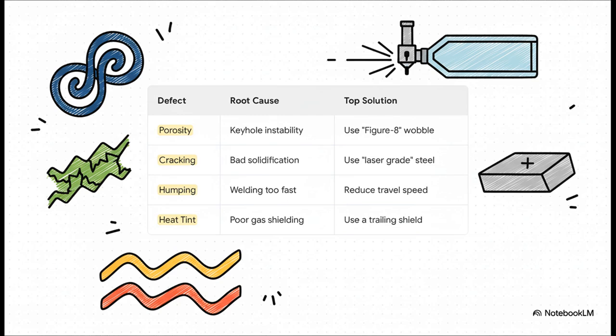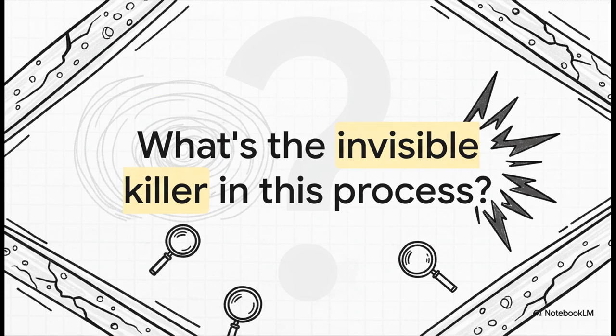Still getting cracks? You need better material, a laser-grade steel with ultra-low sulfur. Seeing that ugly rainbow heat tint? Your gas shielding isn't cutting it. You need better flow, maybe even a trailing shield to protect the weld as it cools. This chart right here is pure gold.